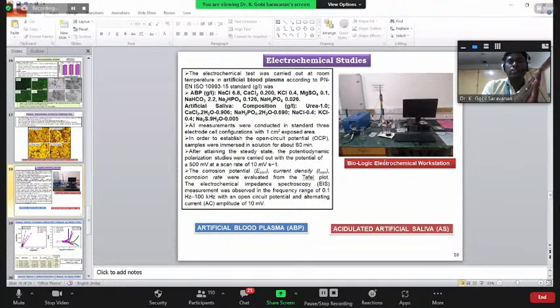Then finally, we come to the corrosion part. For what purpose do we have to do corrosion? After implantation, a lot of body fluids with aggressive ions, sodium, potassium, chloride, continuously bombard the implant surface. At a particular critical condition, the implant surface will form pitting corrosion. Then, if it is stainless steel, nickel and chromium ions will leach out and mix into the bloodstream or deposit on the surrounding tissues. That will cause inflammation, followed by recruitment of immune cells, and then implant rejection.